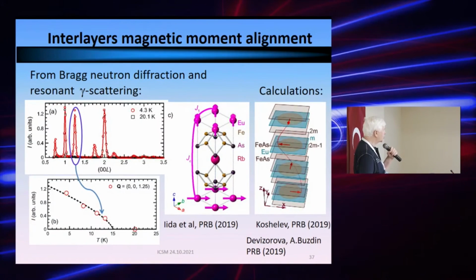Evidently, it's easy to say, but it's hard to understand how one and the same electrons, which are iron electrons, participate in superconducting pairing and at the same time transfer the magnetization. If this were to happen, it should be reflected in a drop in the density of the condensate, not by a tiny amount but by a significant amount, which is not noticed. If it happens via tunneling through other orbitals, that should be identified. So far, I would say that this question is not completely clear.